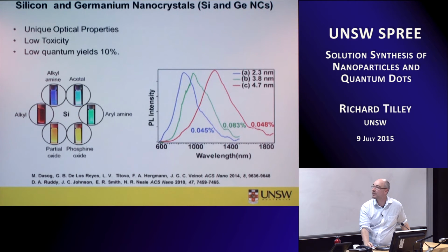But the issue with all of these pretty colours that he's getting, and he admitted this to me, is basically they don't hang around for very long. None of these colours or emissions are very stable at all. So we could take a nice snapshot of them, and that was about it for most of them. The colours that people can reliably and strongly get out are essentially this reddish colour and also the blue colour that we get. They seem to be the two colours that are the most stable over time.